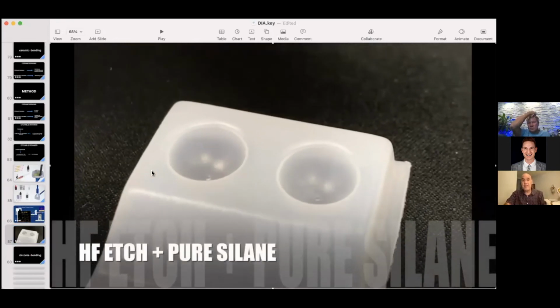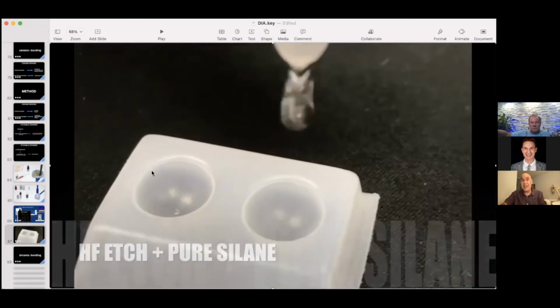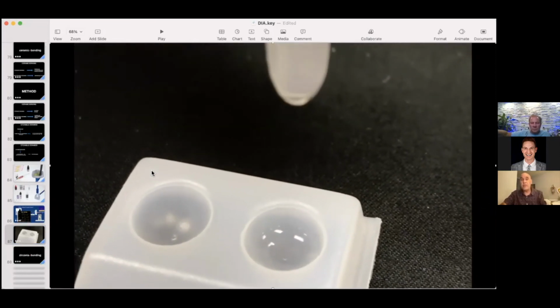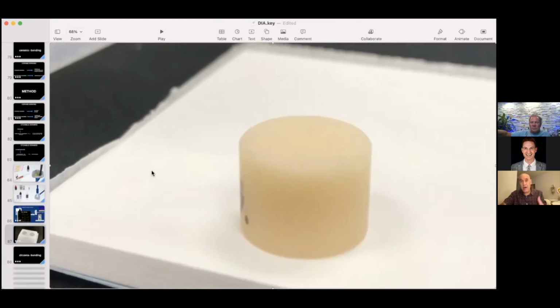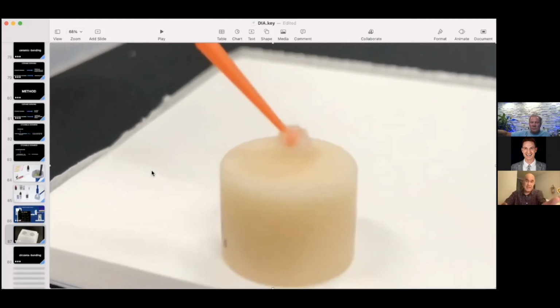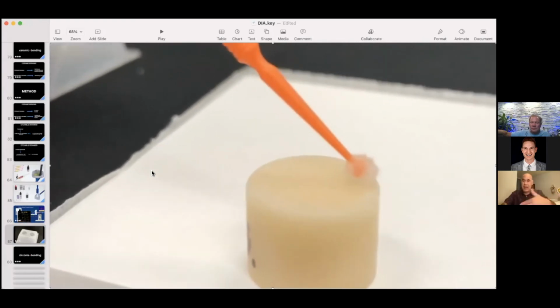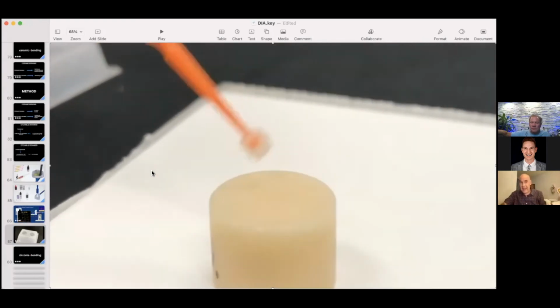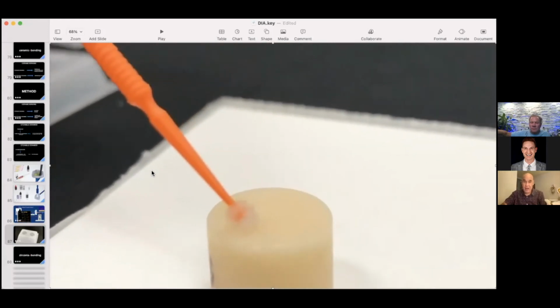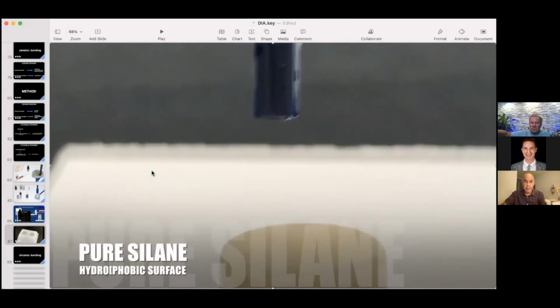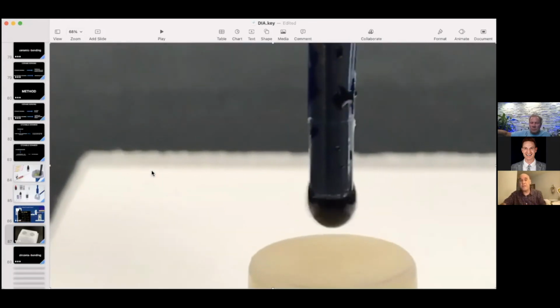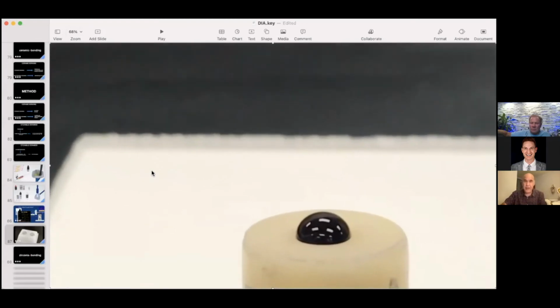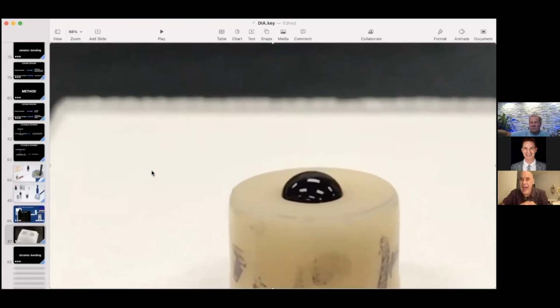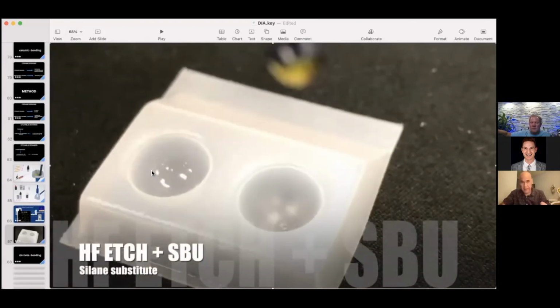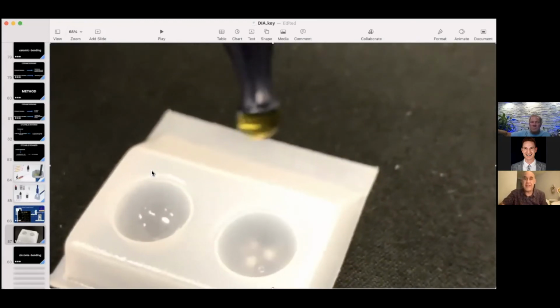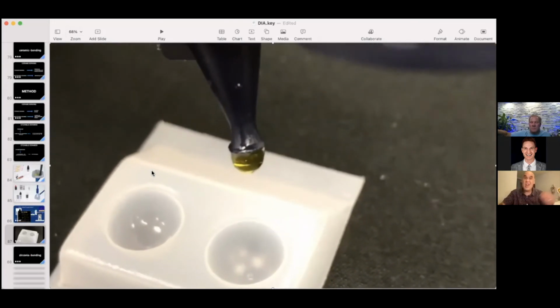So I want to show you a video. This is a surface that I have etched lithium disilicate, and I'm going to place pure silane, right? And here this is an Emax ingot, and I'm placing silane on that ingot. And now I'm going to measure contact angle. I take water, I mix it with methylene blue so you can see it. And the surface should be hydrophobic. Boom, hydrophobic. Why? Because silane has reacted with the surface. This is normal. Now I'm going to take an adhesive that contains silane. In this case, Scotch Bond Universal.